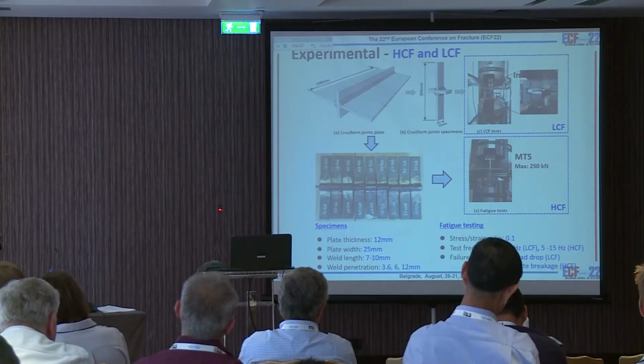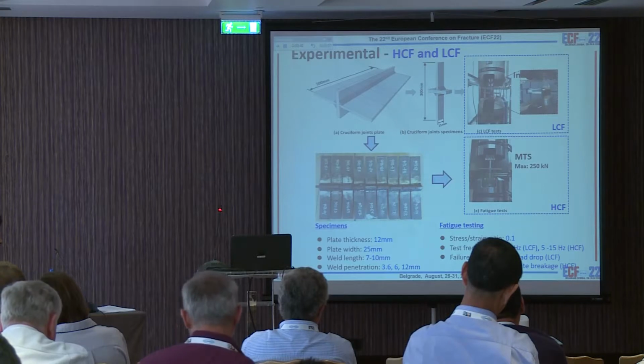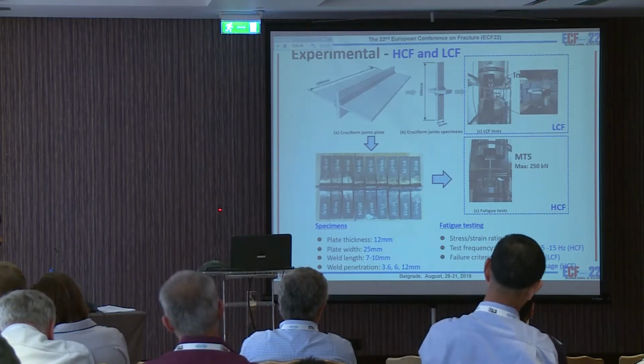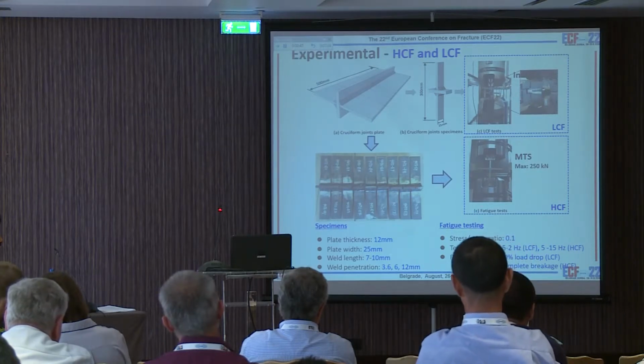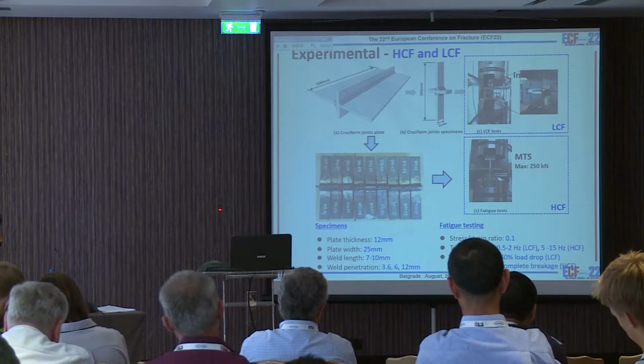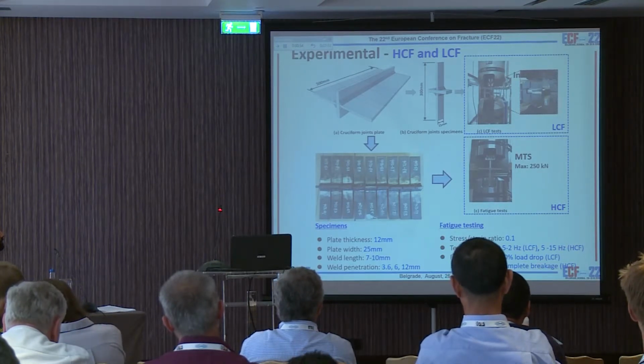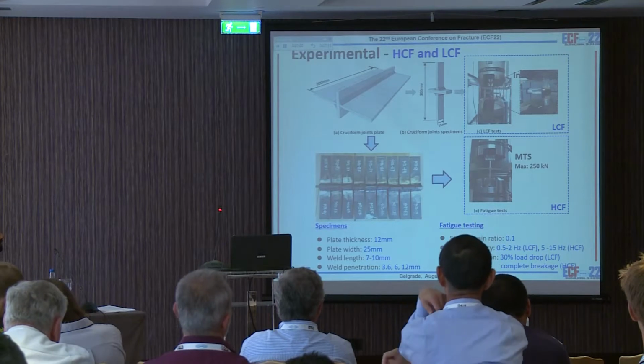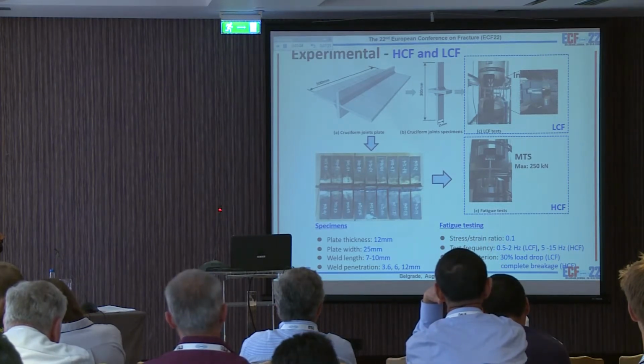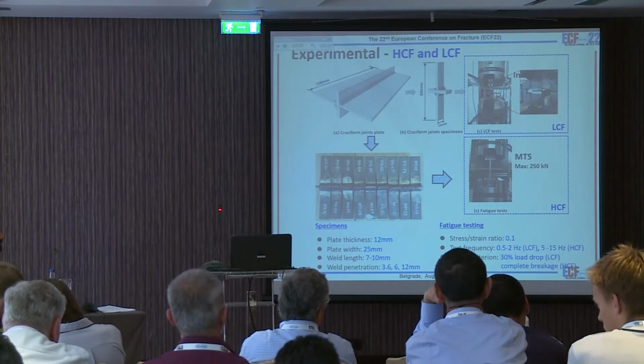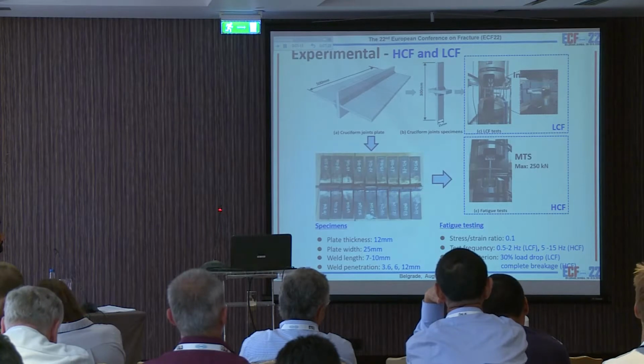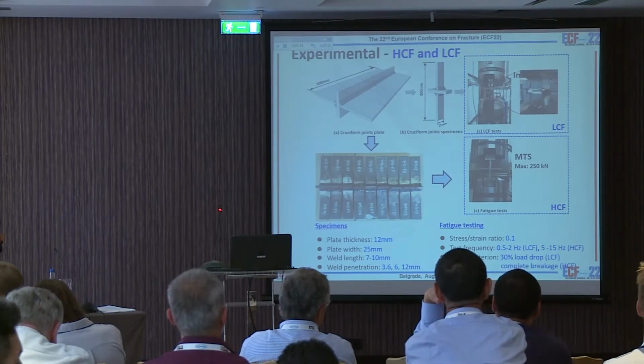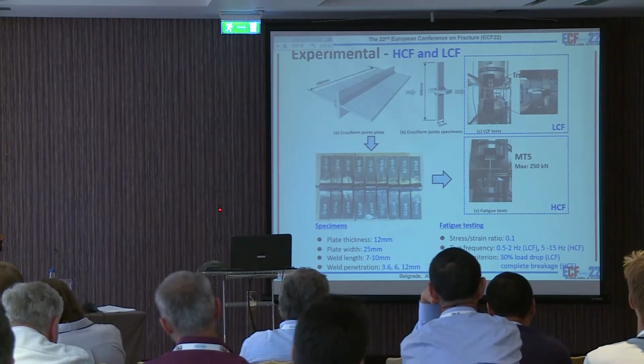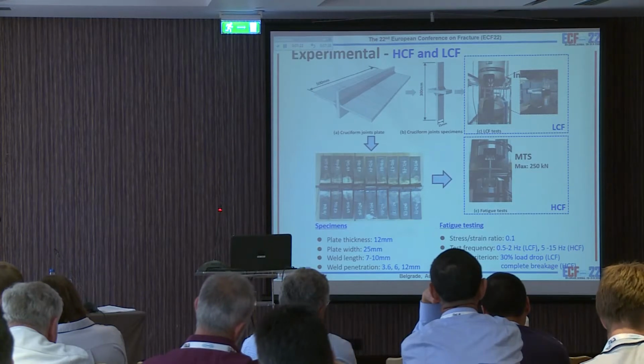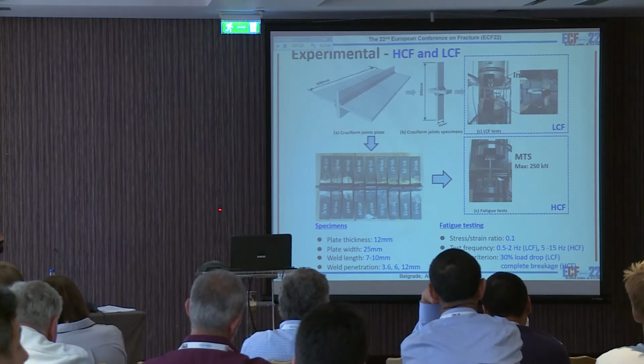For the fatigue test parameters, we use a stress and strain ratio of about 0.1. The fatigue frequency for the low cycle fatigue is low, 0.5 to 2 Hz, and for the high cycle fatigue it is 5 to 15 Hz. Also, the final failure criterion is about 30% load drop for the low cycle fatigue, and for the high cycle fatigue it is complete breakage.